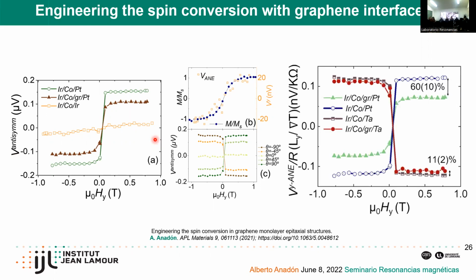So we did this, and we compared also with tantalum samples, and we are observing a similar behavior both in platinum and in tantalum. After removing the contribution from the anomalous Nernst effect, we see that graphene is reducing the total spin conversion in the system. So we think that this is due to a combination of several different things. One is the possibility of introducing a spin memory loss in the system, but also graphene can be highly affected by what has next to it. So platinum and tantalum can affect how graphene behaves in terms of spin conversion. So we have a combination of different things that are pointing both to the same direction, to the reduction of the thermospin voltage in the system.